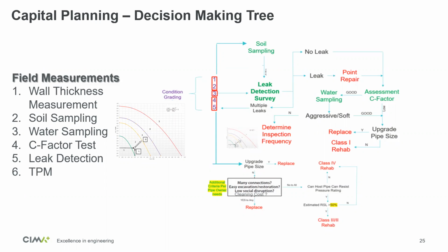If the C-factor came back in a good condition, then we test the water, and based on the water sampling, we will decide what to do. Given the fact that we're talking about potable water, usually the water sampling comes back in good condition. If we find out there is a leak in the pipe, we should ask ourselves if it's a point leak. If it's a point leak, then we will fix that locally, and then we will do an assessment of the C-factor again in order to assess the tuberculation of that pipe, to see if we need to improve the pipe hydraulically by improving the C-factor, or we need to upgrade it down the road.